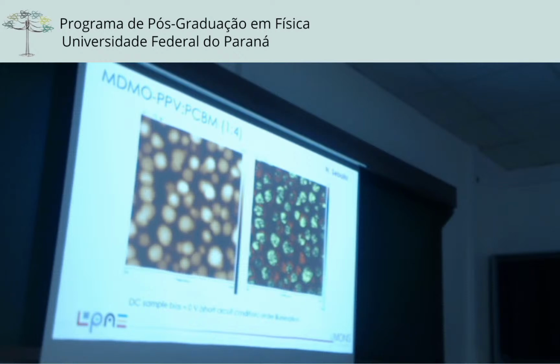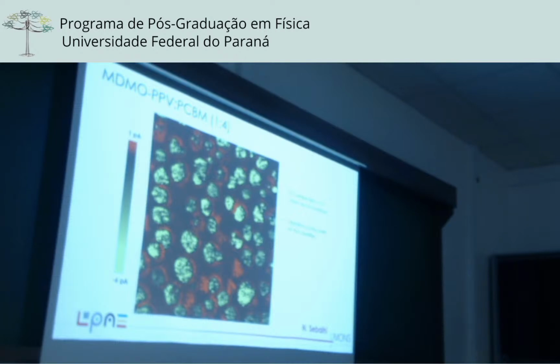Another example is PPV, polyphenylene vinylene, with PCBM. You have the domains of PPV and PCBM. And you can clearly see in red, this is exactly at the interface between the donor and the acceptor. So we have negative current on the crystalline PCBM, and a positive current just at the interface between them. You can see this interface clearly there. And this is why we have this information about the photovoltaic solar cells made of this compound.